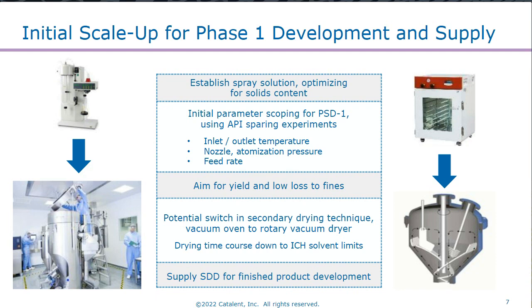So at the lab scale we would determine the solids content, and then through the use of a single spray solution preparation, we would look at exploring different process parameters such as the inlet and outlet temperature, the choice of the nozzle, the atomization pressure, the feed rate, and the interrelationship between these parameters. So this would give us an idea of the processing parameters that we need to be operating with for these initial clinical manufactures.